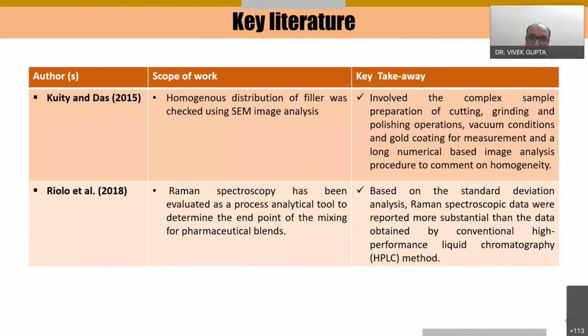Secondly, I want to quote another reference by Riolo et al. in 2018. They found that Raman spectroscopy can be a tool for process analysis to determine the end point of the mixing of pharmaceutical blends. So we have taken the idea from there, and we tried to implement that knowledge in our building construction materials. Based on the standard deviation analysis, they found that the Raman spectroscopic data were more substantial than the data obtained by the conventional HPLC, high performance liquid chromatography method. So we have used Raman spectroscopy to determine the homogeneity of the blended mix.